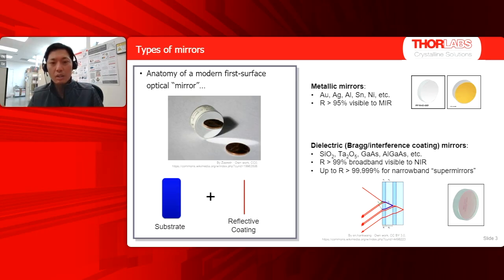We'll be looking at the reflective coating, and these can broadly be categorized into two types: metallic coatings and interference multi-layer coatings. Metallic mirrors, you're probably all familiar with. It's a deposited layer of often gold or silver, aluminum, tin, or nickel. They're very nice. They give you 95% reflectivity or more in the visible through to the mid-infrared. So very broadband, fairly easy to make, fairly cheap to make. However, the physics of the metal coating itself limits you at that level of reflectivity.